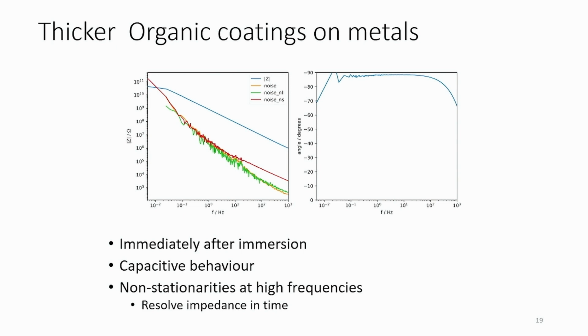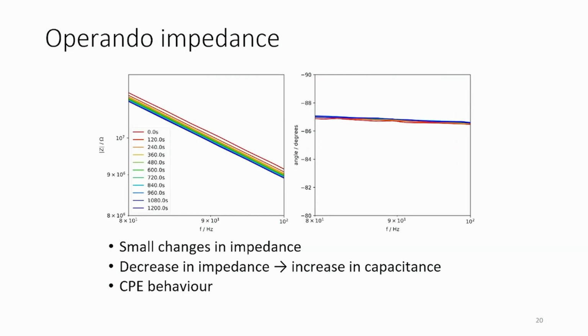So here you see it is a reasonably good measurement, because we don't have non-linearities and so on. So we have optimized the amplitude. And then, due to the fact that we can now measure this instantaneous impedance, we can see what the first electrolyte front is doing with the coating. It is the first contact between the electrolyte and the coating that we can pick up, because we can measure very short times. And out of that, at the moment, we can see what the electrolyte is doing with respect to how it is changing the polymeric matrix and not the interface, because this is information about the coating. So we see small changes in the impedance that we try to relate with the matrix of the coating.